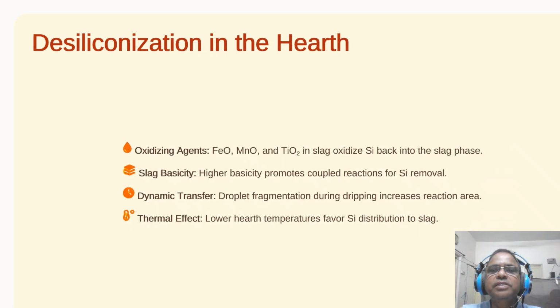So, next slide, which completes our study on desiliconization in the hearth. So, here is a twist. The silicon content actually peaks before the iron reaches the pool at the bottom. Look at these icons for the droplets and levers. Once the iron hits the slag layer in the hearth, a cleanup reaction starts. Elements like FeO and MnO in the slag act like magnets, pulling the silicon out of the metal and back into the slag phase. We call this desiliconization. If we keep the hearth at the right temperature and high basicity, we can actually scrub some of that silicon away at the very last second.